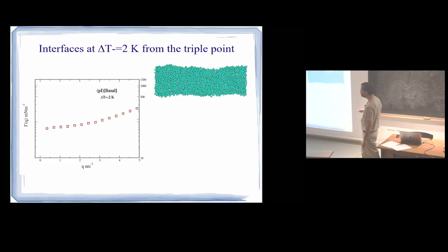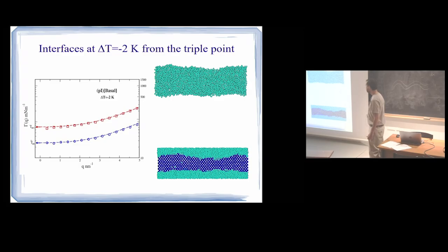It's converging to a value because I am at a fluid interface, which is rough. Okay? And one can test that by fitting these to the expectations; this extrapolates at q=0 to a value that is exactly the surface tension of my model. I can test that independently. Okay? So it works.